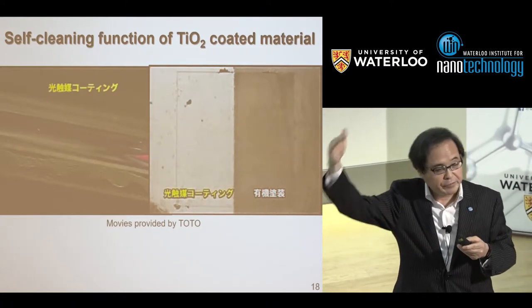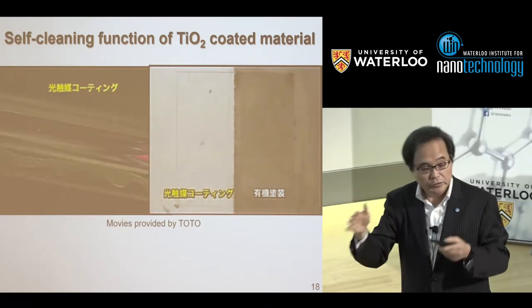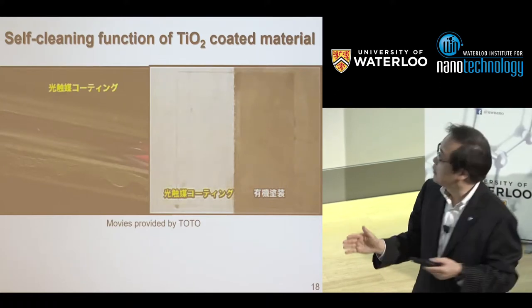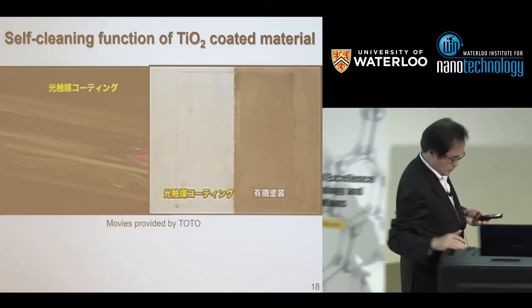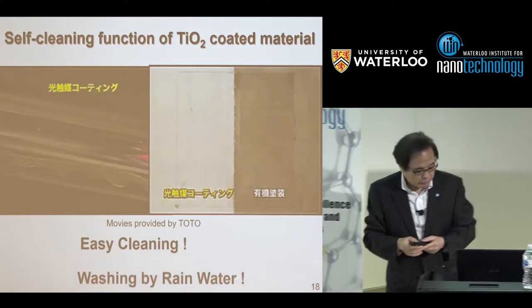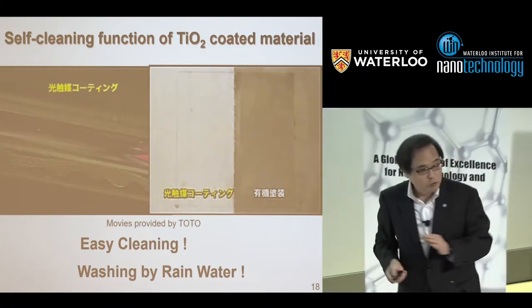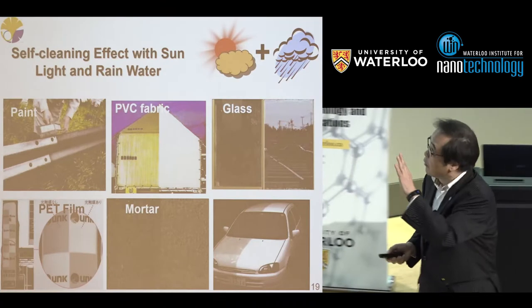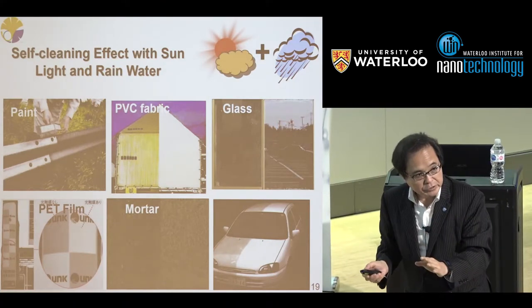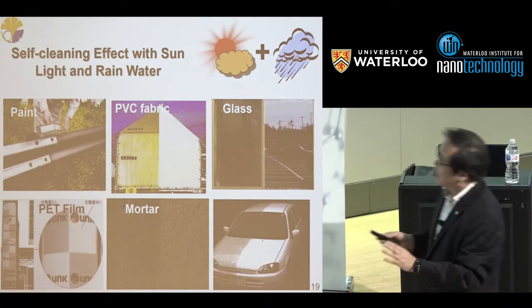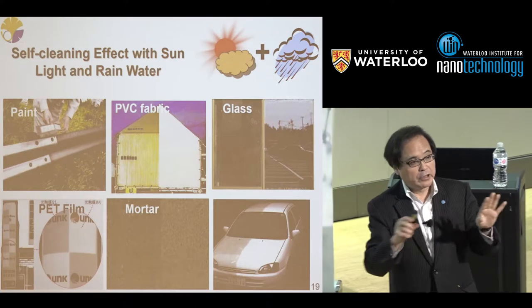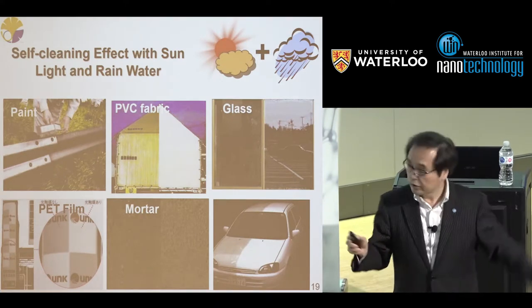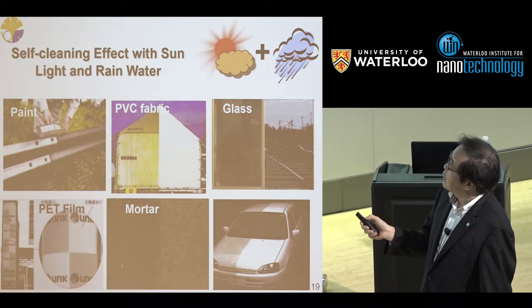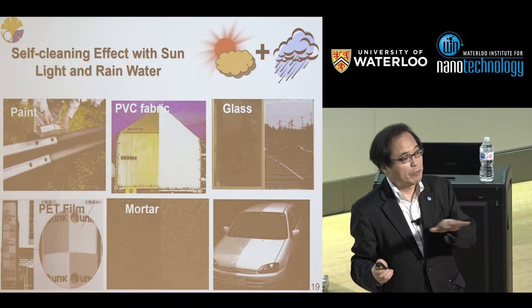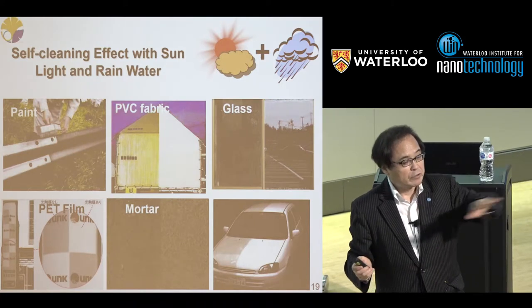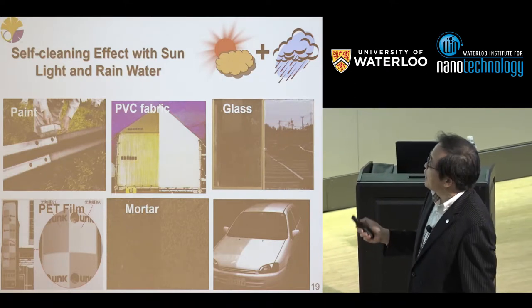So if we expose this substrate outdoors, then the surface is always super hydrophilic. So by combining both, the easy cleaning washed by rainwater, and the photocatalytic decomposition reaction and photo-induced hydrophilic reactions, the titanium dioxide coated material keeps clean when we expose it outdoors. And paint, fabric, glass, PET film, even for PET film we developed the binders. So we have such transparent binders, and mortar and even cars.